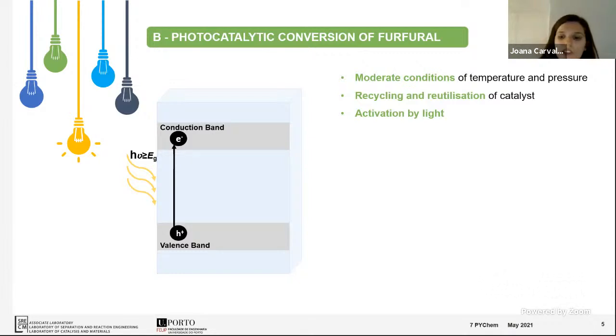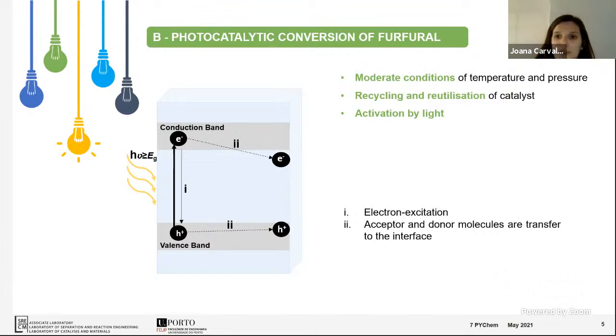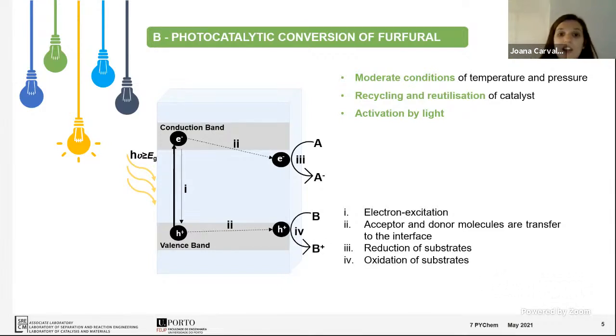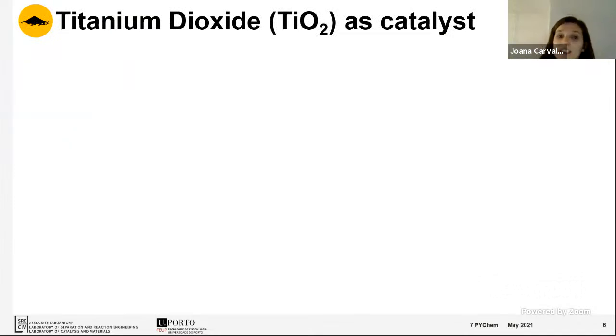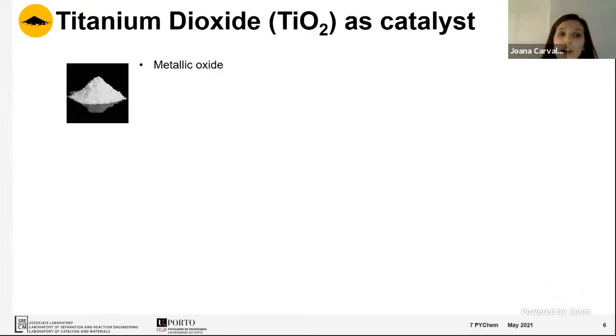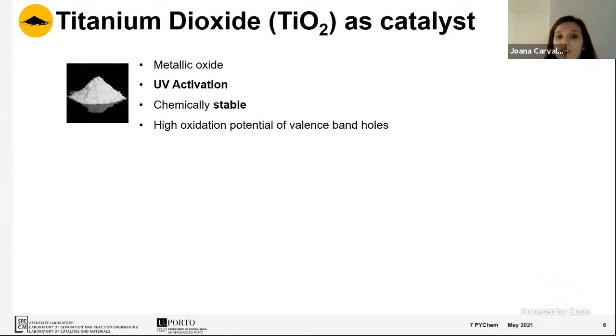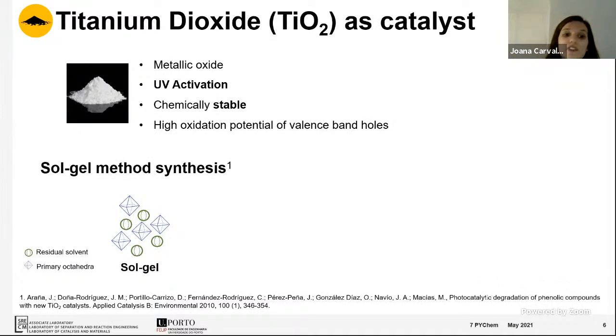When we have favorable conditions, these reactive species are transferred to the surface of the semiconductor, allowing the reduction and the oxidation of substrates. In this case, we are allowing the reduction of furfural in order to produce furfuryl alcohol. In photocatalysis, it's very important to choose a photocatalyst. In this way, I talk about titanium dioxide. It's a benchmark photocatalyst, used in many areas, and presents great activity in some of them. Titanium dioxide is a metallic oxide activated by UV radiation. However, it presents a high chemical stability and a high oxidation potential on valence band holes. There are many ways to synthesize titanium dioxide. In this work, I used a sol-gel synthesis method.